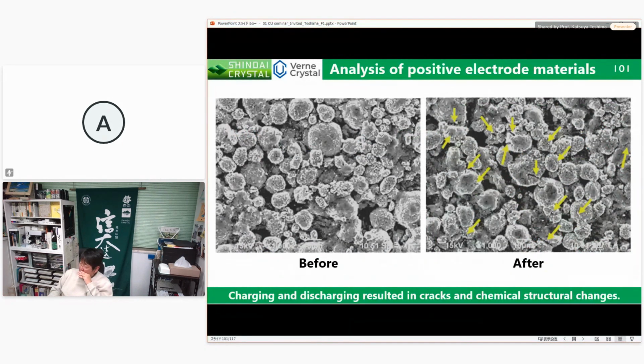LIB particles, NCM523, were used to determine the cause of deterioration. A 1000-cycle charging and discharging test was carried out. After 1000 cycles, several cracks occurred, as shown by the yellow arrows. It has been previously reported that cracks are generated in the positive electrode after long periods of use.